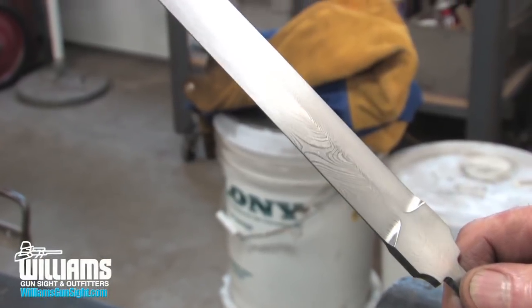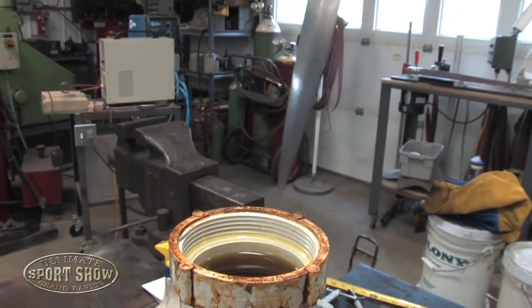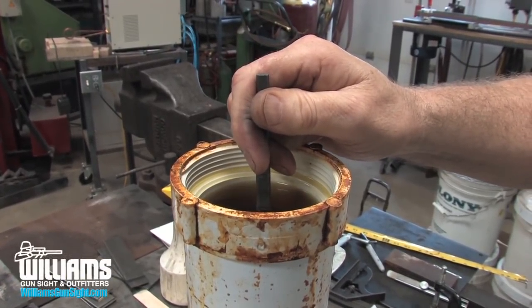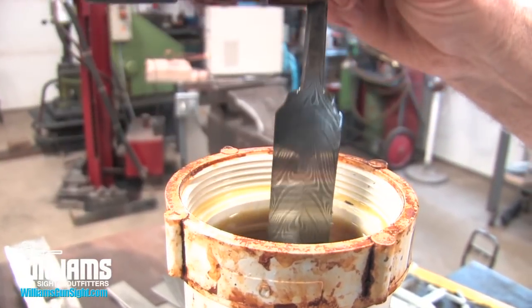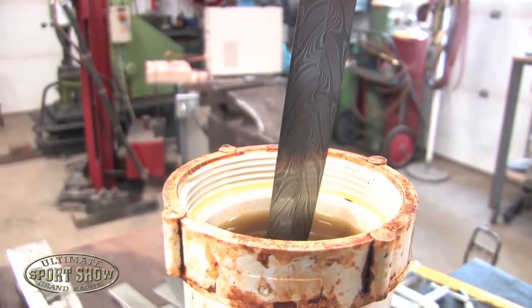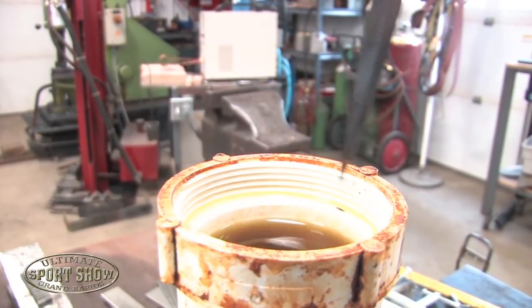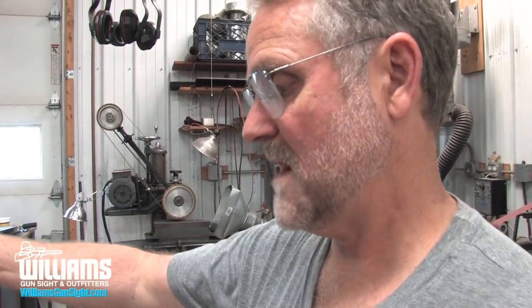As I had previously said, there's contrasting layers of steel in this blade, and we've welded the steel together, built up a certain layer count. This is a twisted pattern, so we've twisted that layer count in that steel. Now we're going to etch it to help bring the pattern out. What the etching does is it etches away a little bit more on one than the other. The nickel's resistant, and the etching will make the steel with the manganese dark. The steel with the nickel will remain silver or lighter, and the etching just really brings the contrast out. What we have here is an etched blade, and I'll do that many times, maybe 4 or 5 times, and each time card it off with some very fine paper, like 2000 grit, and that's your pattern though. That's it right there. And that was a twisted, double twisted strand.